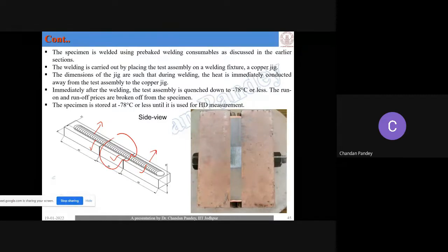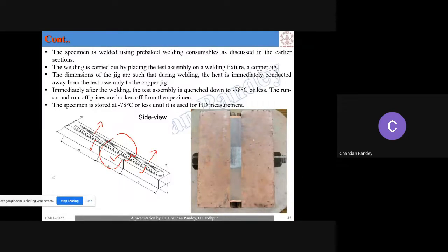Now after making that three-piece sample, we fix it in the copper fixture. This is the copper fixture, and we fix the three pieces, and after that we deposit a layer over the surface of the workpiece. We deposit a layer with the optimized welding process parameter, and once the deposition is done, we remove the run-on and run-off pieces, because we require only the center piece.